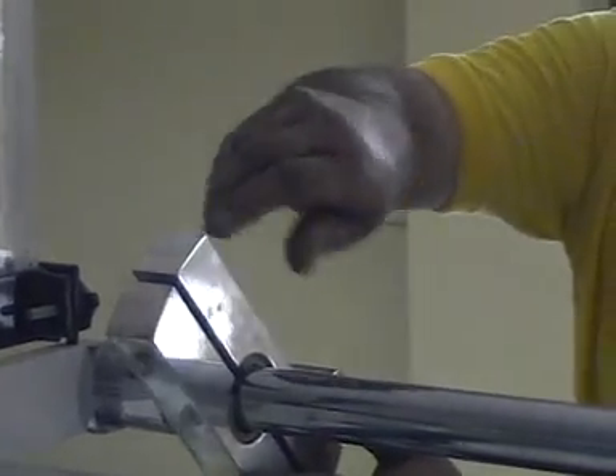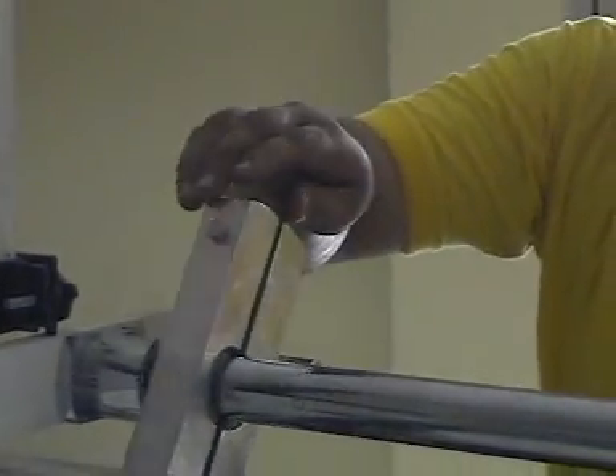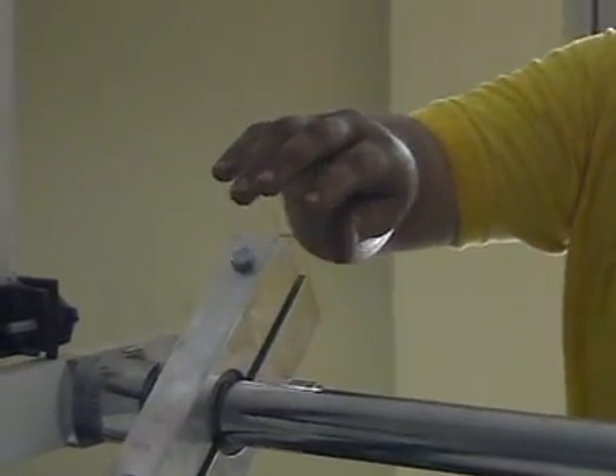If the coating is not proper on the film like this and you find certain marks or wrinkles forming on the film, then tighten the film brake to avoid these wrinkles. By tightening the film brake, the wrinkles on the film get removed and you can find wrinkle-free lamination on the machine.